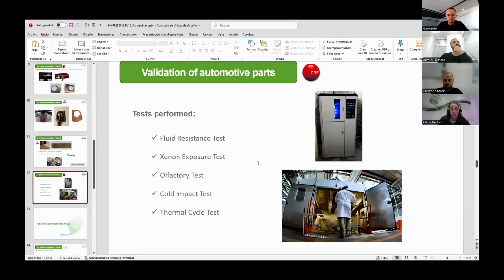And considering the light aging, we can say that the coating, as I mentioned also previously, has proved that the material is better with this coating. It stands the aging through the lighting. It's better with this coating that Fraunhofer developed.